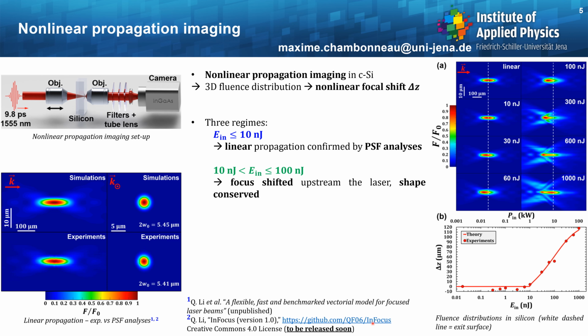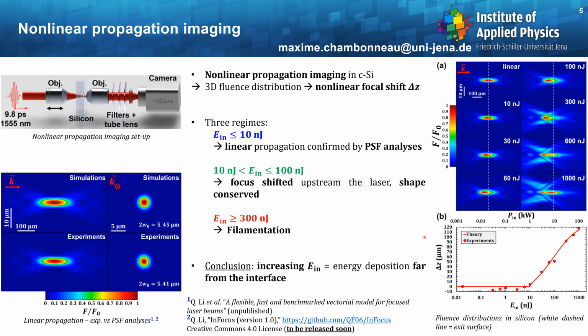In the case of intermediate energies, so between 10 nanojoules and 100 nanojoules, one can see that the focus is unambiguously shifted upstream the laser, but the shape is overall conserved. Finally, in the case of extremely high input pulse energy, one can see that we reach the filamentation regime, as you can see here, with multiple focal positions. So to conclude on this data, one can see that increasing the input pulse energy leads to an energy deposition which will be far from the interface.